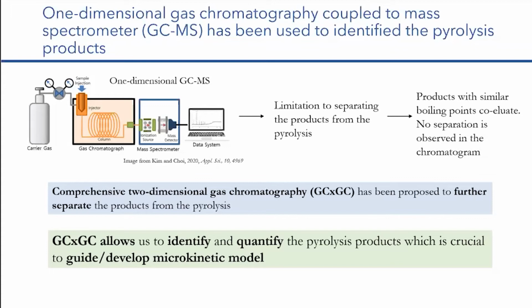For example, we will obtain different hydrocarbons according to different carbon numbers. So we can have different C6 hydrocarbons, and all of them have similar chemical and physical properties. So it's very difficult to separate just using one-dimensional GC. So for this reason, we want to study the pyrolysis using comprehensive two-dimensional gas chromatography, because this allows us to separate the products from the pyrolysis.